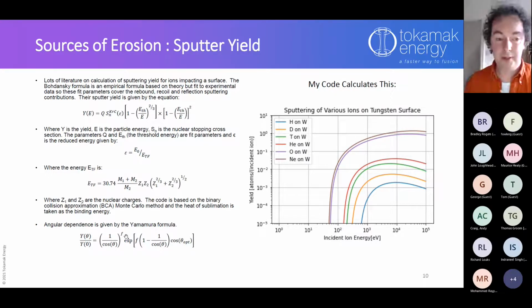And what I've done is basically take the equations from the published literature, put it into a bit of code, so we can do a bit of programming, so we can end up drawing curves like these. So this is data that I produced from the literature. This is predicting the sputtering using the available theory, and you'll see what happens is that you've got your ion energy here, and so these two curves, you can probably see the big ones here with a high sputter yield. So this is going up to a sputter yield of 1, which, if you remember, is where I said that's bad news. This is for neon and for oxygen.